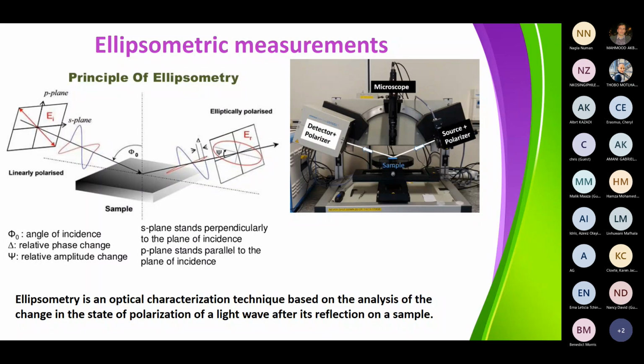And the incident beam goes through a polarizer, which transforms the light into a linearly polarized light. And then the beam is reflected on the sample. During the reflection, the sample induces a phase change, and this will change the polarization of the reflected beam. In fact, we have an elliptic polarization after the reflection. And this elliptic polarization depends, of course, on the sample that you are studying. By analyzing this elliptic polarization, the device can deduce two ellipsometric angles called psi and delta, where delta is linked to the relative change in phase, and psi is linked to the relative amplitude change during the reflection.